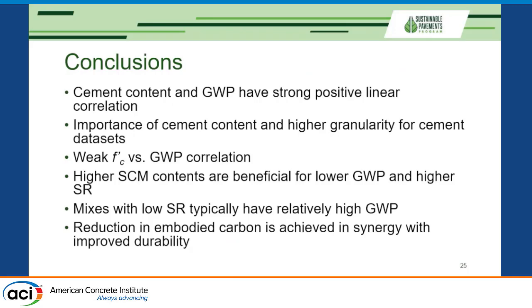This is my final slide. So based on this study, we have concluded that cement content and GWP have a strong positive linear correlation. Cement is a very high contributor. We need better data for cement to understand exactly the levels of contribution. We couldn't find any correlation between compressive strength and GWP, but we could find that durability and relatively low GWP often go hand in hand.